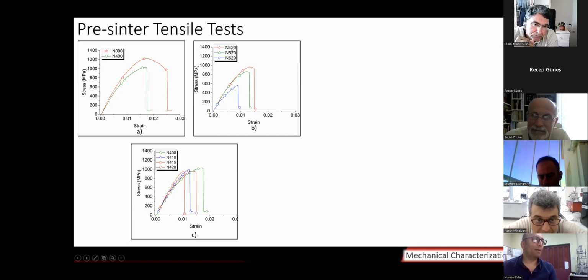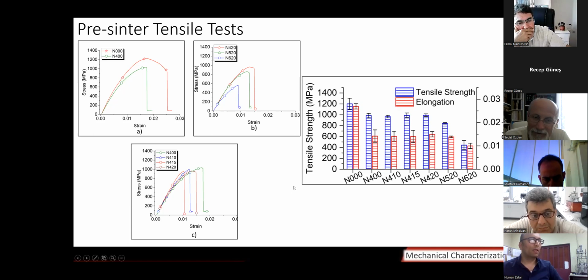And increasing the core diameter in the pre-sinter wires has resulted in both reduction in the tensile strain and reduction in the tensile strength of the wires. And overall, if you see in the pre-sinter state, we cannot see that there is a dramatic difference in the tensile behavior of all wires. They have a similar tensile strength, and the tensile strengths do not appear to be very different from each other, but please check the scale, it is 0.01 and 0.02. 100%, twice. Yes, 100%. Yeah, let's say twice, okay?